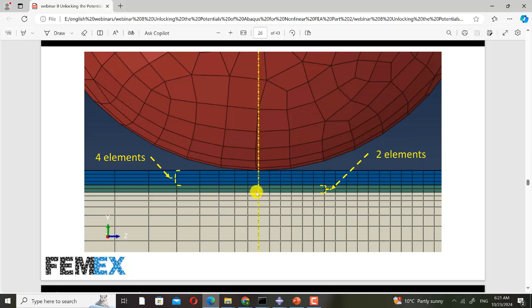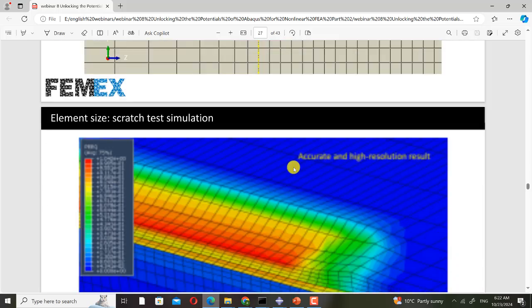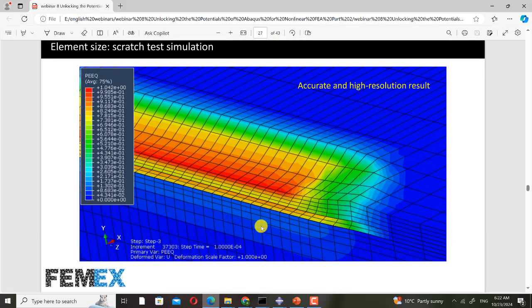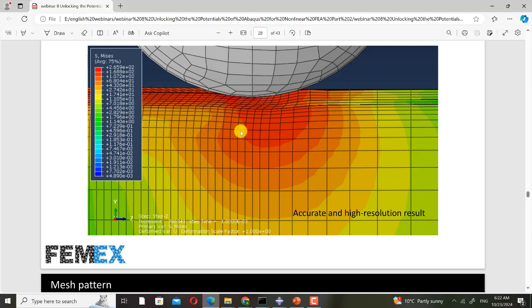And in this simulation, we have two layers, and along the thick one, I have used four elements, and along the thin one, I have used two elements, okay? To have accurate calculation of stress along the thickness. So when you do all of these, then you will have such accurate and high resolution stress contour, okay? And also, I have validated this result, and it is like the result in its reference paper. And also here, you can see that we have an accurate and high resolution result. And this is because of using small elements in the stress concentration region and larger elements in the far fields. So you will have both the accuracy and efficiency.